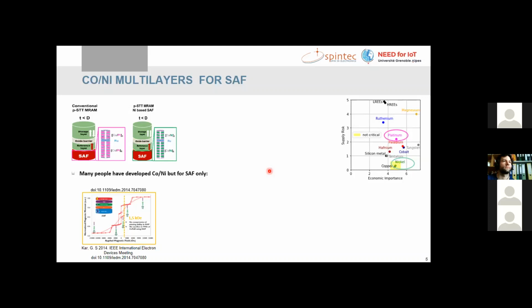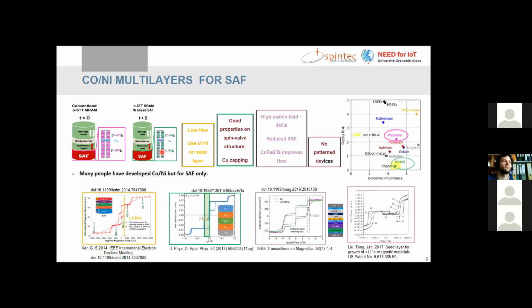So there has been a lot of literature, a lot of advancements in the field of cobalt-nickel multilayers development. But actually, for the case of the synthetic antiferromagnet that needs to be used in MRAM, there have not been so many studies. And from what I've seen, normally they have difficulties of having a high switching field, which also defines the retention that I was speaking about before, this capability of having good thermal stability for the reference layer, so that it does not switch when switching the storage layer. And also, in some cases, they had some problems going to high temperatures during the annealing process, which will be problematic for the CMOS compatibility that has also been spoken about before.